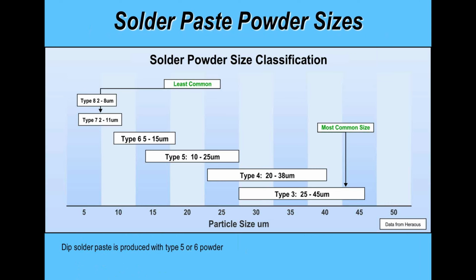Now, if we look at solder paste as a material, generally speaking, up until probably a couple of years ago, the majority of people would use a type 3 solder paste. And we're talking about a material that has a range of particle size between 25 to 45 microns based on the IPC criteria. And still, a lot of people use type 3 material.